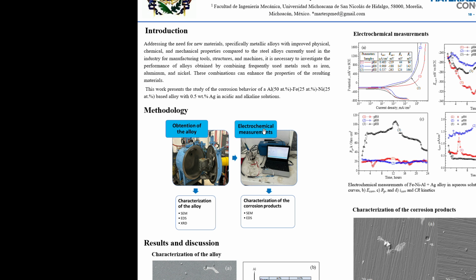Some samples were polished to a mirror finish with 0.5 micrometer diamond particles and micro-etched to be characterized by scanning electron microscopy and X-ray diffraction. Additionally, Vickers micro-hardness measurements were performed applying a load of 200 grams.